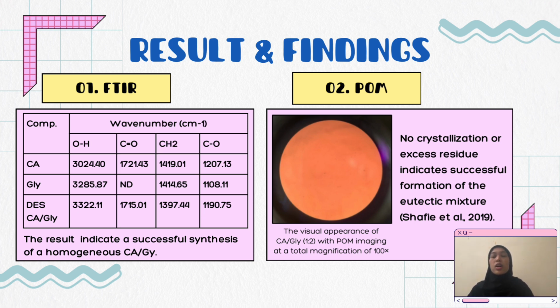The wave numbers for citric acid for the C double bond O group and the CH2 group had decreased to 1,715 and 1,397 respectively during the formation of the DES. Additionally, the C single bond O group had shifted from 1,108 in glycerol to 1,190 in the DES mixture. These shifts reflect the hydrogen bonding and other interactions between the groups, or the HBAs and HBDs, indicating a successful synthesis of a homogeneous DES.